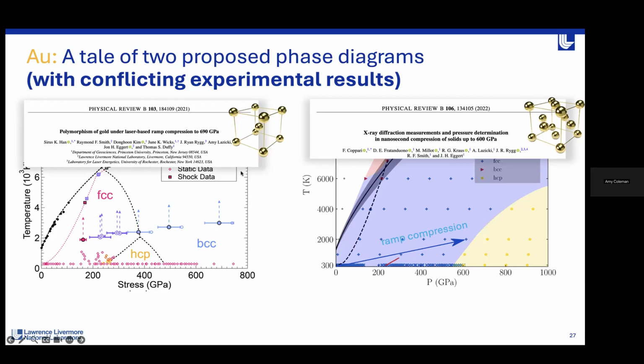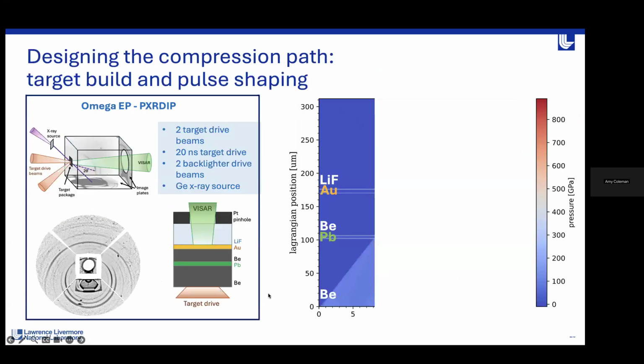So what we've got here is really the perfect use case for this shock ramp compression path that I've been describing. What we could do feasibly is design a series of shock ramps where we start off with a relatively low shock and probe at a lower temperature, then incrementally increase this shock state, probe at increasingly higher temperatures, and step up to see where this BCC phase comes in. This would give us an opportunity to constrain this. And so that is precisely what we did.